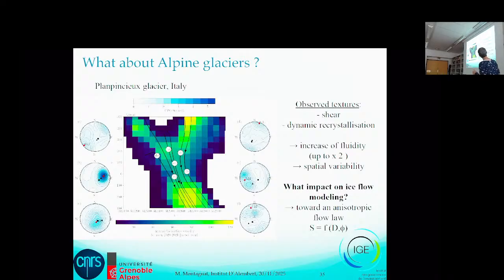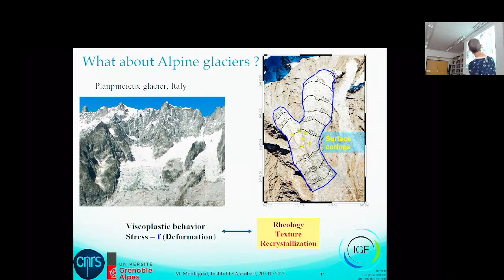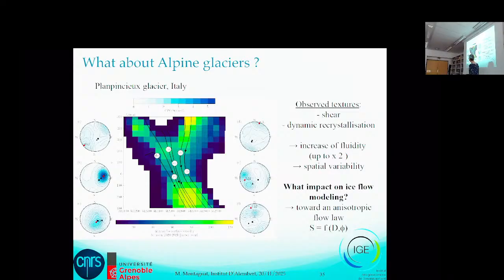Maybe I can take just one example. Okay, let's take this example. The texture is not very strong, but still it exists. It's number C. And here C is more or less in the middle of the larger part of the glacier that we see here, in a part that is flowing quite smoothly. But it's flowing on a slope, and therefore the main deformation that this ice is following is shear. The texture that we are measuring is in very good agreement with the amount of shear that we are expecting in this area. Good point for us.